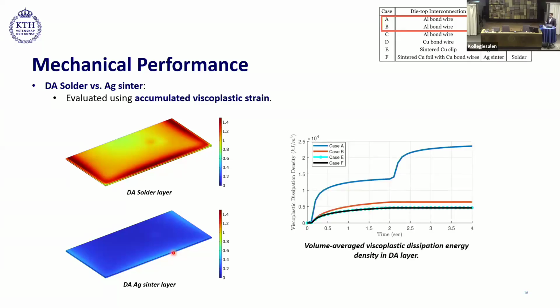We also calculate the volume averaged viscoplastic dissipation energy density in the die attach layer. And we see that the solder layer, which is represented by this blue curve, exhibited higher viscoplastic dissipation energy density than the silver sinter material, which is shown by these plots here. Therefore, we concluded that the kind of material we have inside the package changes the mechanical performance and thermal performance at die attach.